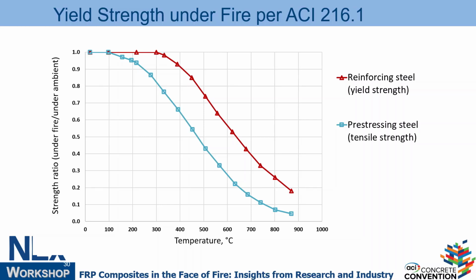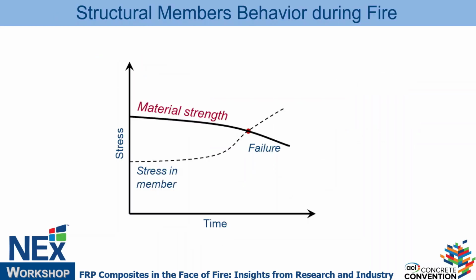This is just to represent the typical trend, because when we draw the high-strength steel, let's say the 7-wire post-tensioning strands, that changes the molecular structure a little bit and makes it more susceptible to fire. Add to that, most of the time, at service they're under stress. It may not look significant, I mean, they're close to each other. However, it is really a big difference, because if you look at, let's say, 600 C, while the mild steel is close to 50%, the pre-stressing steel is close to 30% plus minus, right? So that means it degrades much faster for the same thing. That's why I never understood why the concrete cover is the same for pre-stressed and reinforced concrete, because if I do thermal analysis, I'll find they degrade faster than this.